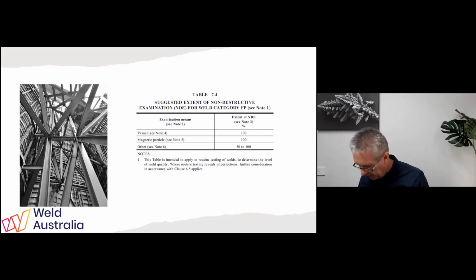We then look at mag particle, note 5. The use of mag particle is unusual except for supplementary inspection after visual inspection for the types of structures and applications on which the standard is intended, and their use is usually restricted to repairs. And then when we look at note 6, for plates with thicknesses of not less than 20 mm, a portion of each multi-pass butt weld shall be examined ultrasonically to determine whether there are any transverse cracks within the weld metal. So it's now stipulating a plate thickness in relation to what you can do there.